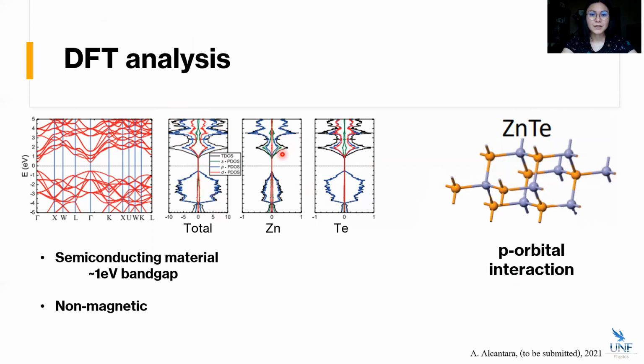If we go ahead and look at the zinc, we can see that the S and the P orbitals are interacting for the local density of states for zinc. And then the tellurium is exhibiting a P and D interaction. And because the S and D orbitals don't interact in local density of states, this can just be labeled as a P orbital interaction for the zinc telluride.